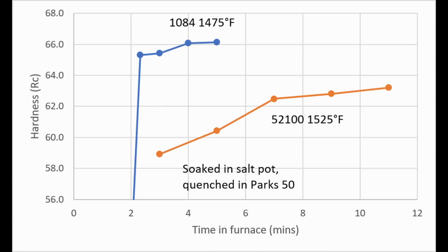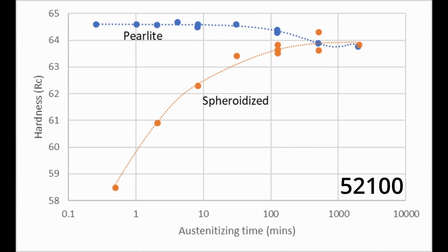I will note that this experiment with 52100 and the 1084 was with factory annealed steel, which has a relatively coarse spheroidized structure. And with the relatively coarse structure, it takes a longer soak time. If you use a pearlite starting structure instead, it is much less sensitive to soaking time. Now, this isn't always a good thing, but I have recommended this in specific cases such as heat treating in a forge where you don't have good control over the temperature.